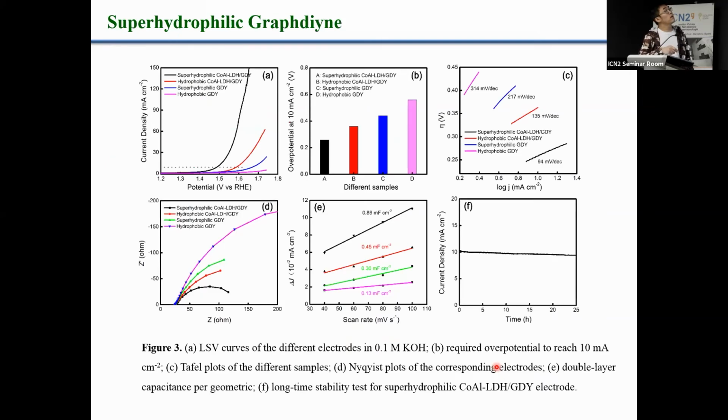And this is some testing of the OER reaction: the LSV, the overpotential, Tafel plot, EIS, electroactive area, and the stability. We can see the LDH-assembled superhydrophilic graphdiyne shows much enhanced activities compared to the hydrophobic one.